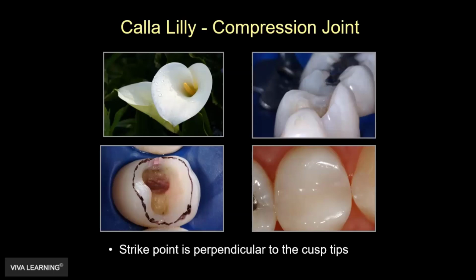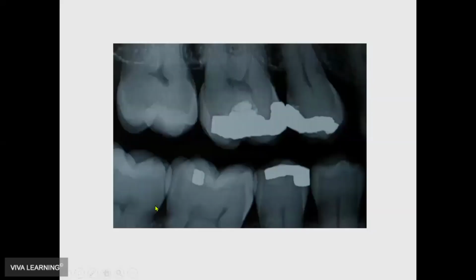If you have a funneled-shape calla lily that goes almost up to the cusp tips, you have a receptacle that can distribute stress and not accumulate stress on the adhesion interface, that you can run that material into a tapered funnel, and that these are enduring for 8 to 15 years.